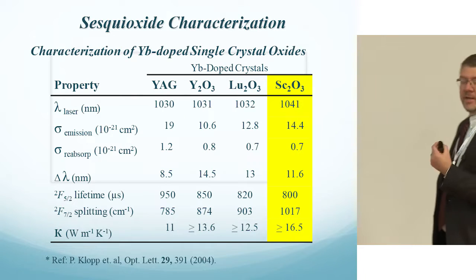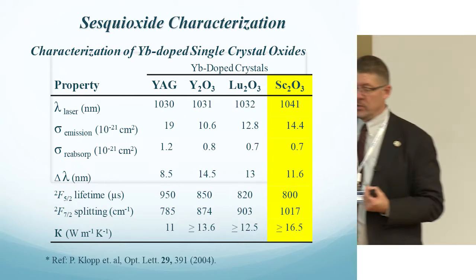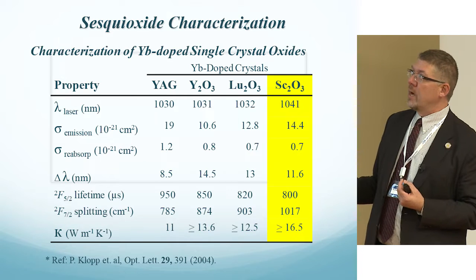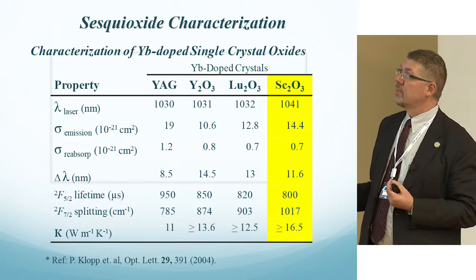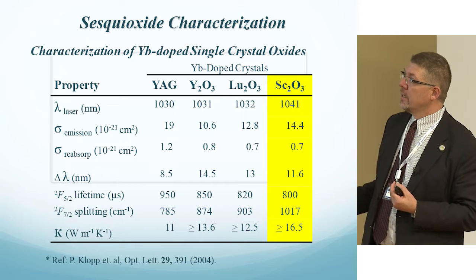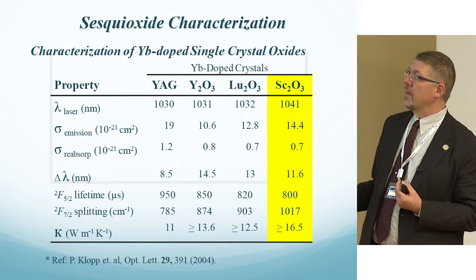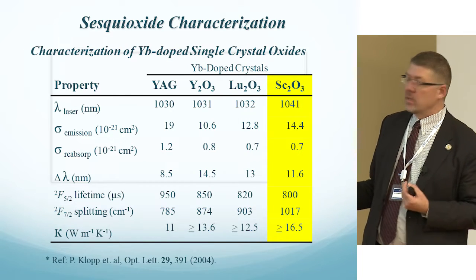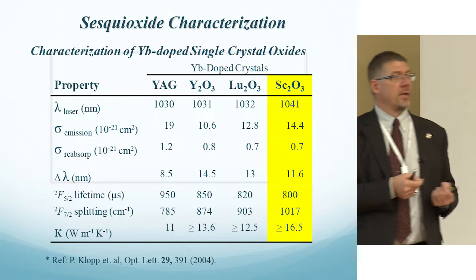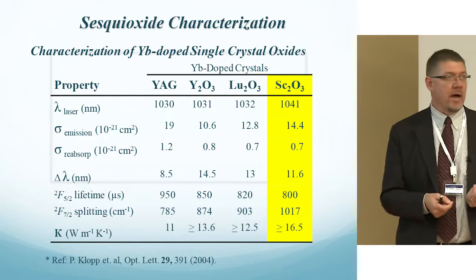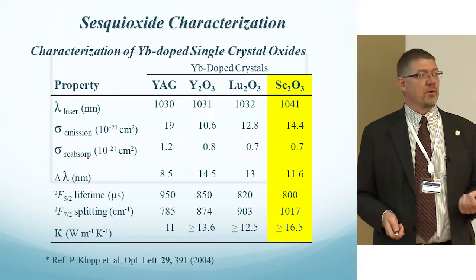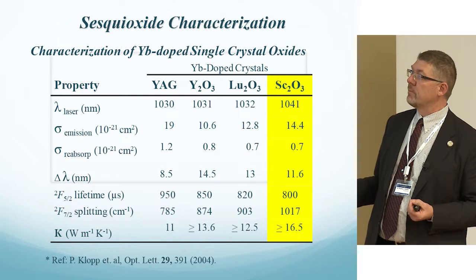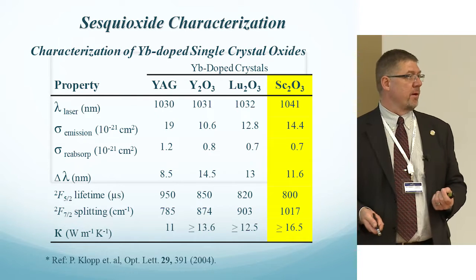One of the other materials that's getting a tremendous amount of investigation currently are the sesquioxide materials, primarily ytterbium doped sesquioxide. And the real reason is that it's right down here in the thermal conductivity. When you're pumping a laser material hard, you want to get the heat out. And the best way to do it is to have a good high thermal conductivity. And compared to something like YAG, it's 50% better thermal conductivity.